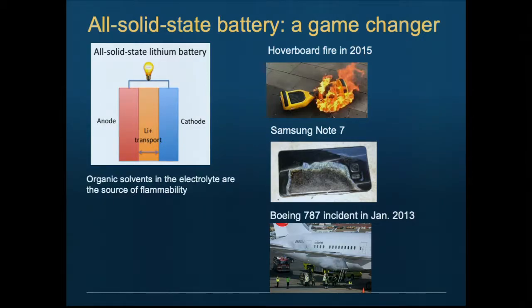The primary driver for solid state is safety. The reason is that what makes a lithium battery flammable is not the lithium, it's the organic electrolyte. We use an organic electrolyte, a carbonate solvent, which has a very low flash point. And so the typical incident in the battery is one of two. Cells get punctured in an accident, electrolyte leaks out, you're in a high voltage environment, you have sparks and things blow up on you. Or the other one is you have an internal short.